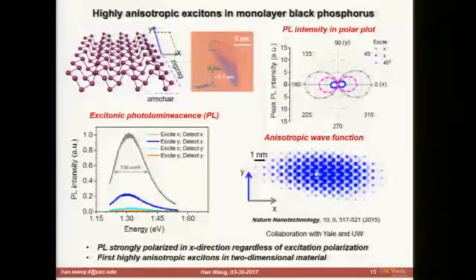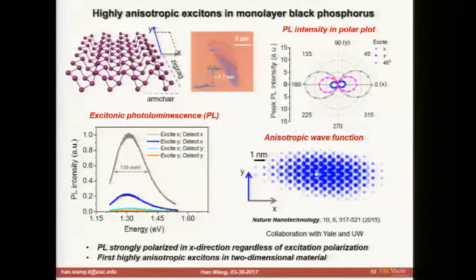In 1D materials, it's because of the one-dimensional confinement of carriers. In black phosphorus, it's due to the low level of crystal symmetry — similar behavior, but very different fundamental physics.